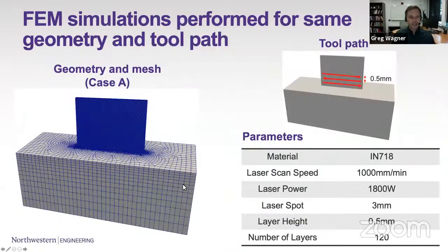To that, of course, we can add our simulation. So we simulated the same case using our finite element code. The mesh, or representative mesh, is what you see on the left here. The toolpath was fairly simple, just a single scan wall with a layer height of 0.5 millimeter. So this is a directed energy deposition where the scale itself is fairly large compared to a typical powder bed method. And so we were able to simulate that same case.